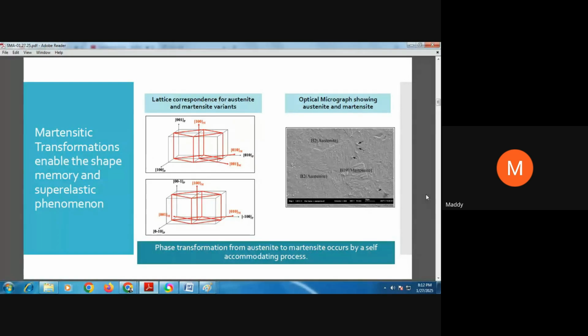So the question that naturally comes out is, what causes these shape memory and superelastic phenomena? If we delve deeper, just like what you have in steel, the phase transformation that happens in nitinol that gives these properties is due to martensitic transformation. Now, martensitic transformation by itself is a diffusionless transformation, so there is no long-range diffusion of atoms, and there's no chemical change. There's no change in chemical composition of the phases before and after the transformation. But unlike steel, in NiTi, the martensitic transformation that enables shape memory is recoverable. And it's mainly because of what's called twinning.